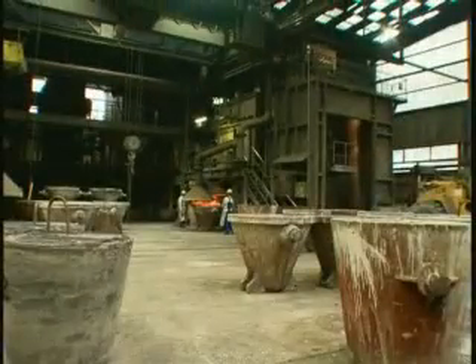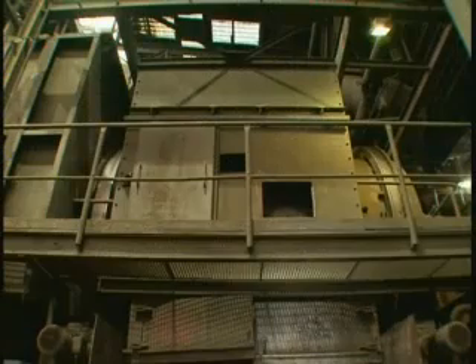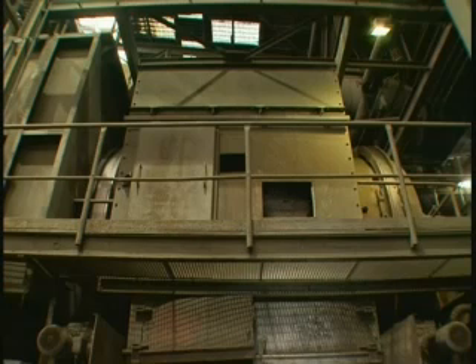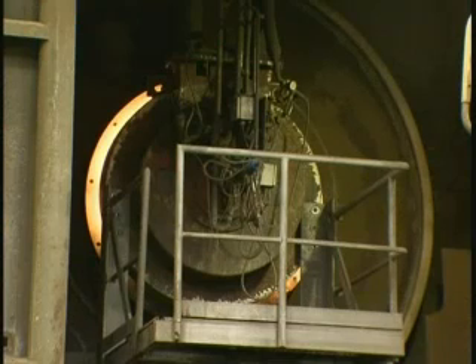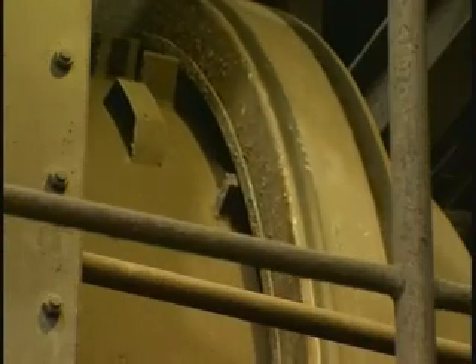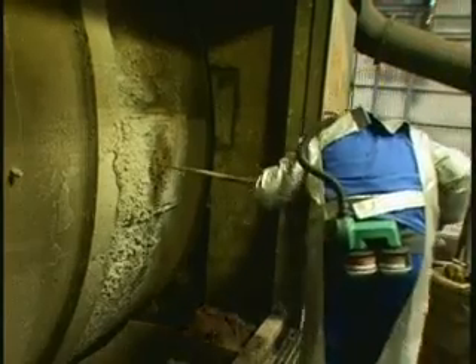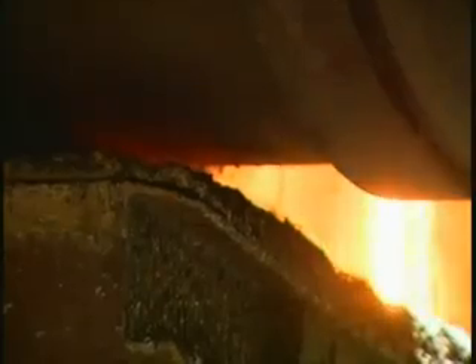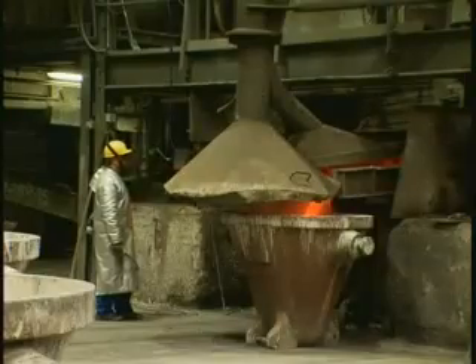The copper-bearing residue, the so-called copper dross, from the refinery and the vessels of the QSL reactor is converted to copper matte in a long rotary furnace. The matte is sold to a copper smelter as feedstock. The lead still contained in the dross is recovered and returned to the refinery.